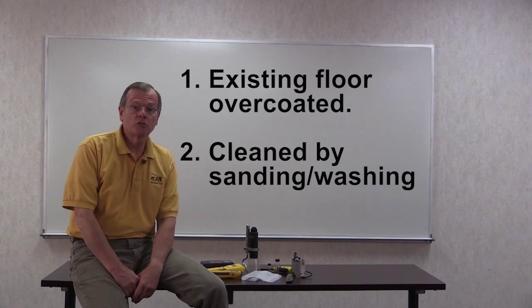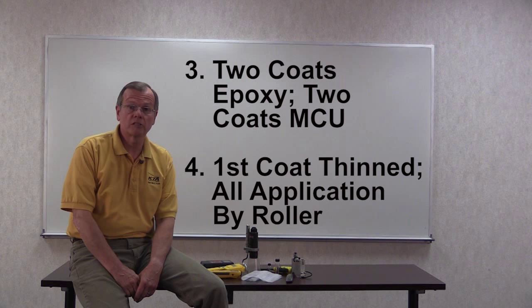Keep all of the information you collected in mind when you start conducting the tests. And for this project, the background information revealed the following. The existing floor was overcoated. The floor was cleaned by sanding and detergent washing. Painting consisted of two coats of epoxy, chips broadcast while the epoxy was still damp, then two coats of clear moisture cure urethane. The first coat of epoxy was thinned. All application was done by roller.